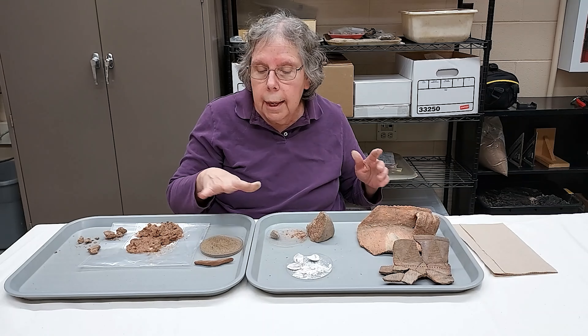Pottery is going to have a mixture of the clay and the temper. You'll be able to see that variation between particles of sand or crushed rock or some other temper and the paste. In a piece of natural material like sandstone, you'll see the individual sand grains and they might kind of look like they're in layers — but the material when you zoom in will be all uniform sand grains. Likewise with similar materials, the texture will be all uniform without that variation between clay and temper that we would expect with pottery.